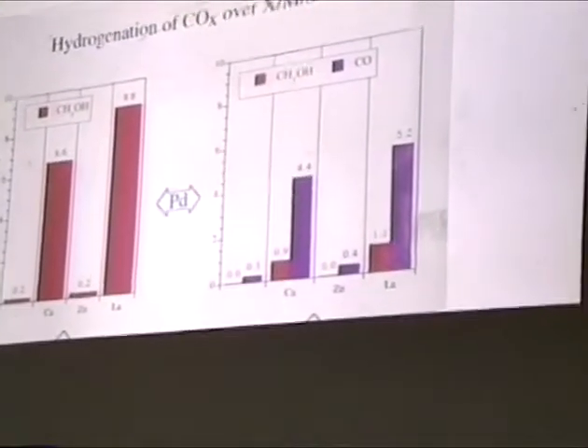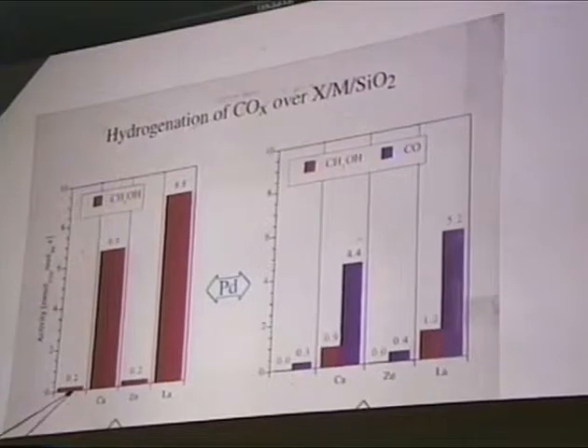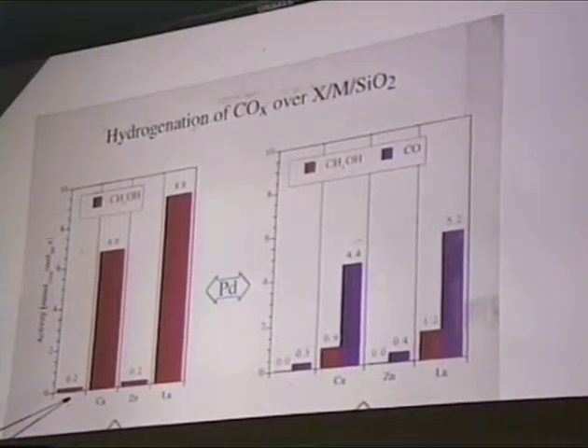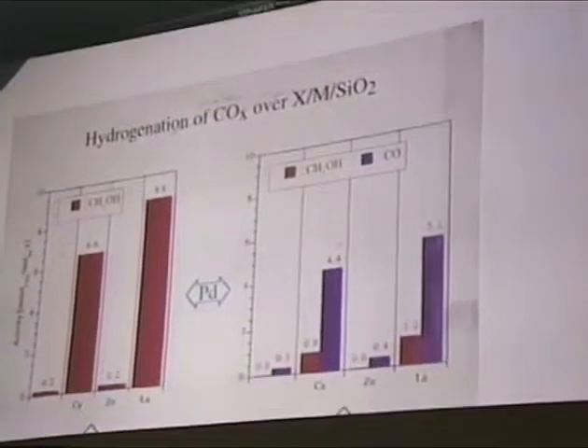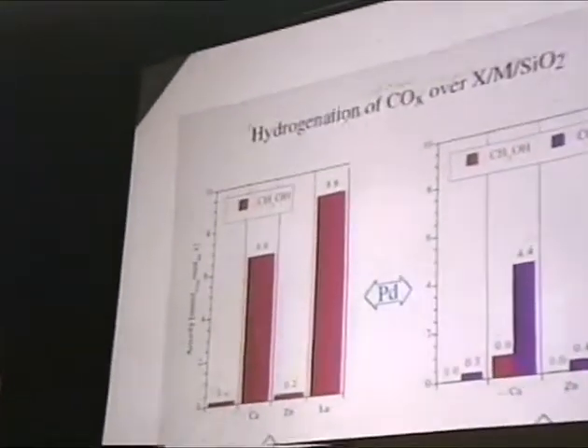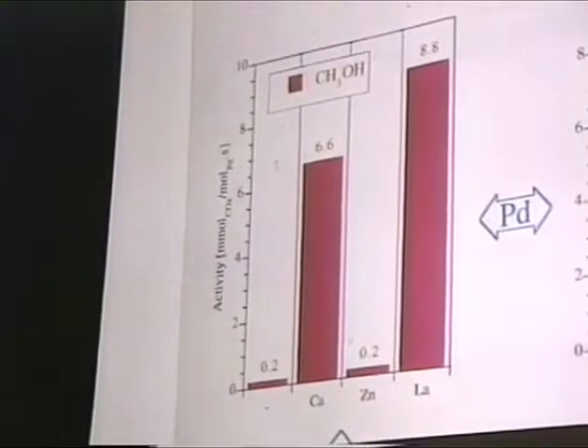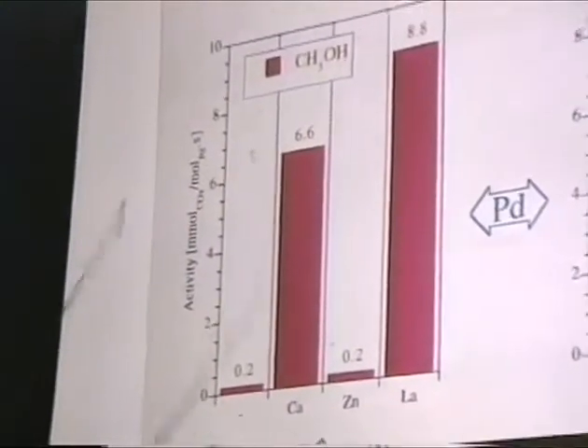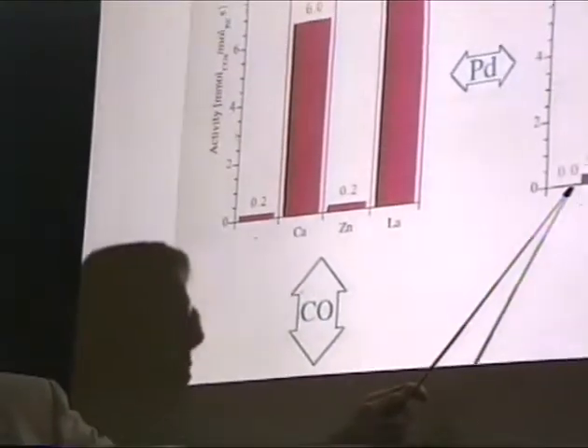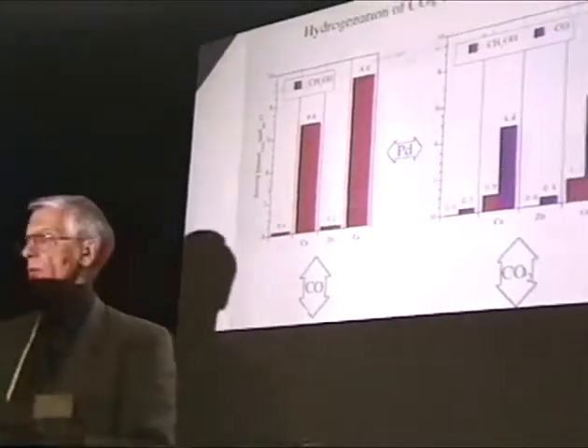So that brings me to my final slide. I summarize a few of these examples here. The palladium on silica is having a very low activity for the methanol, but the moment you promote it with a basic promoter like calcium or lanthanum, the earth alkaline or the alkaline metal oxides, it's very good. When you do that with CO2, you see that the palladium on silica itself is not good. But when you then promote it, it's good again.